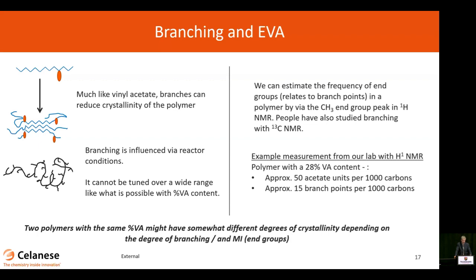So here's an example, again, taken from our laboratory, where we took a 28% vinyl acetate copolymer. We used an NMR method where you essentially determine how many end groups are in the polymer. And if you have some knowledge of the molecular weight of the polymer, you can infer or estimate the number of branches per 1,000 carbon units. And so you see in this example here, there's about 15 branch points per 1,000 carbons, and there's about 50 acetate units per 1,000 carbons.